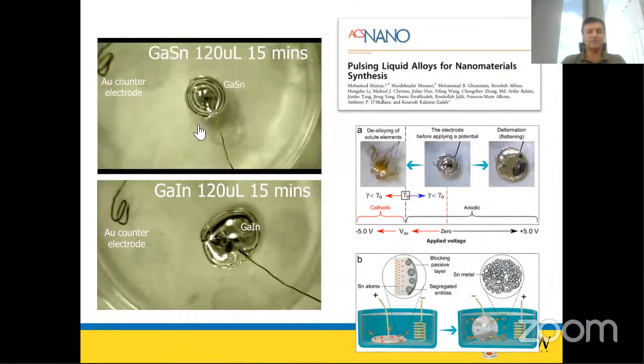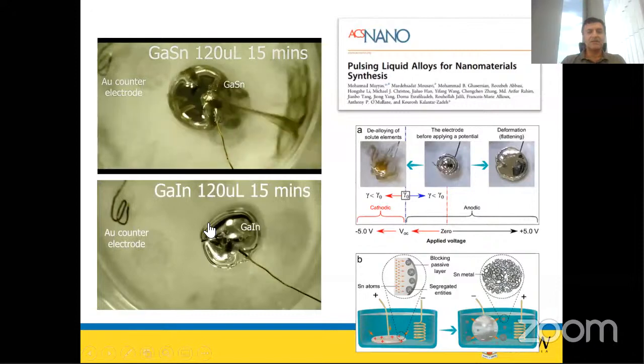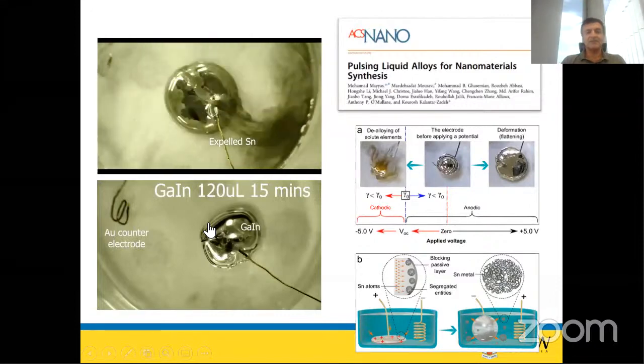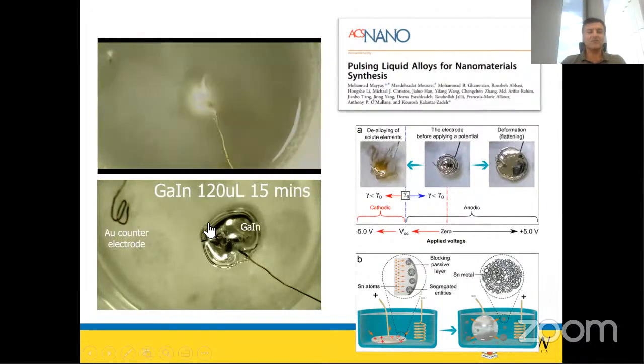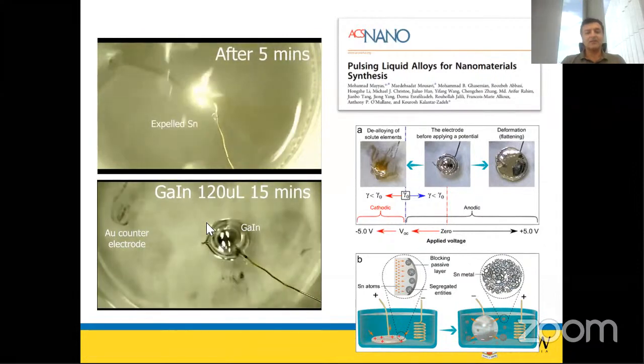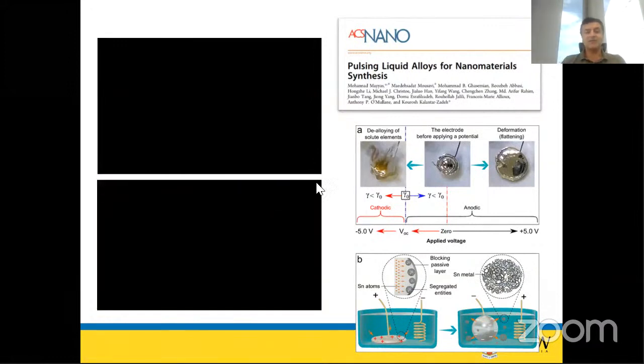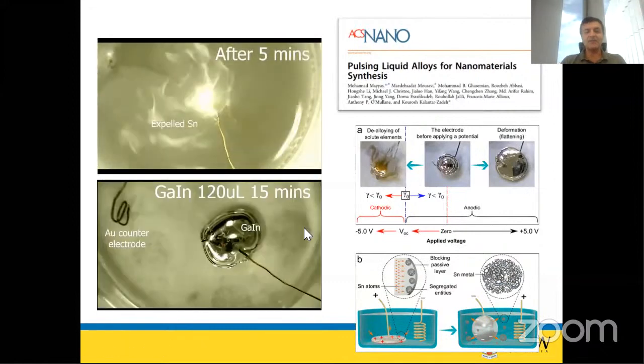Look at this one. Here is the example for tin. Tin nanoparticles are coming out. And this is the example for indium. Indium particles come out as well, but there is a difference between indium and tin. One of them templates onto the surface, and one of them comes out as nanoparticles. The nanoparticles, as you see, make the environment very cloudy, like a milky shape. But here, they come out as sheets, which are black. And these sheets are relatively large in size.